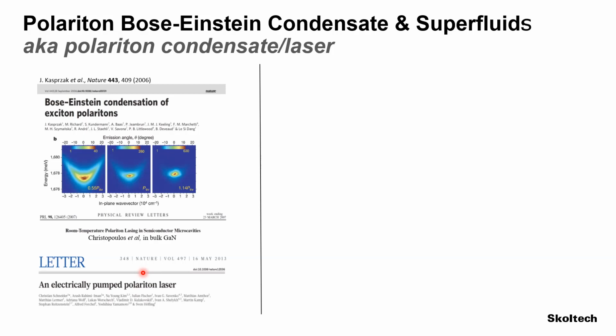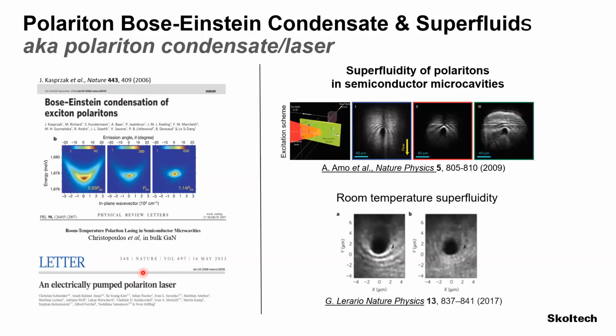So moving on, in 2009, there was the first demonstration of an indication of superfluidity from polariton condensates, where practically what they were doing, they were injecting polaritons resonantly at the ground polariton state, and they could see that by increasing the density of polaritons, they could really create a superfluid that goes through a defect without creating ripples. Yeah, and this is a property of superfluids, when you really go through a defect without scattering. And that was again repeated in 2017 at room temperature with organic microcavities.